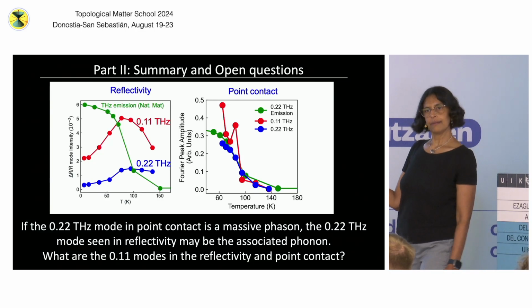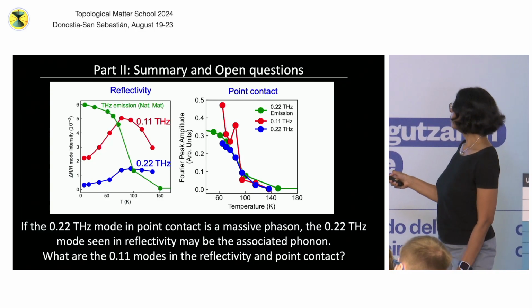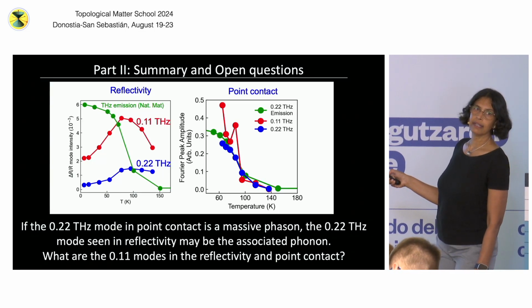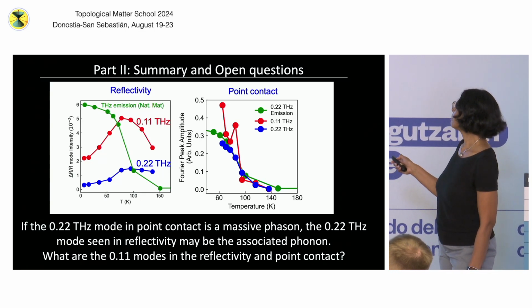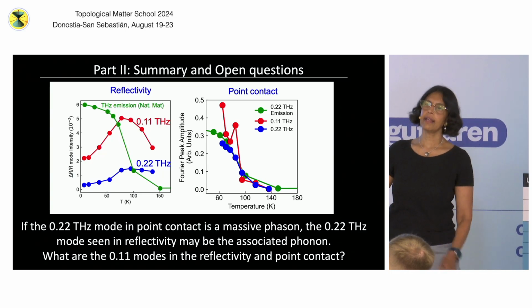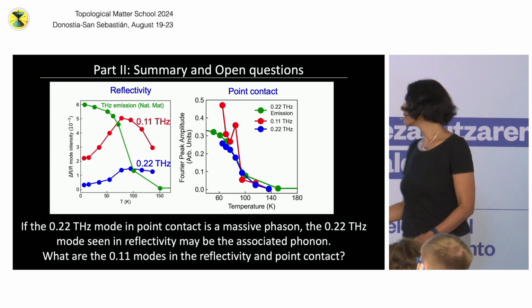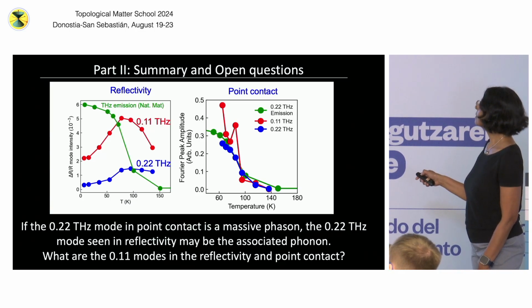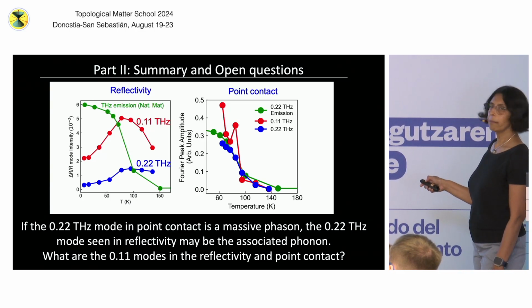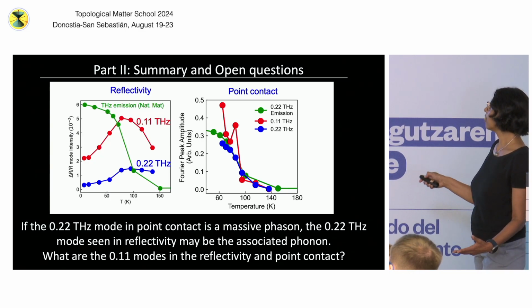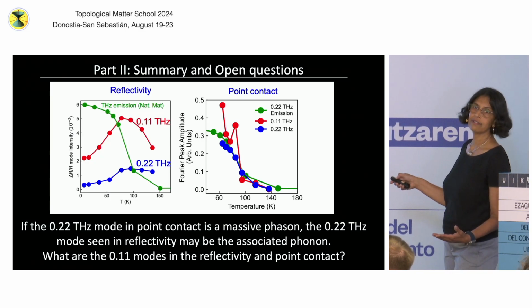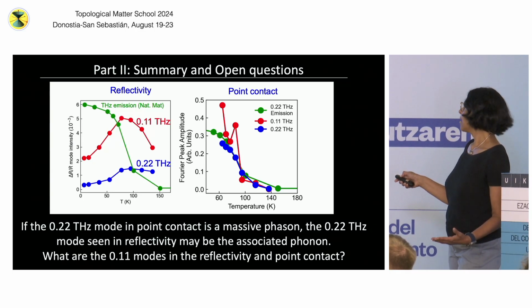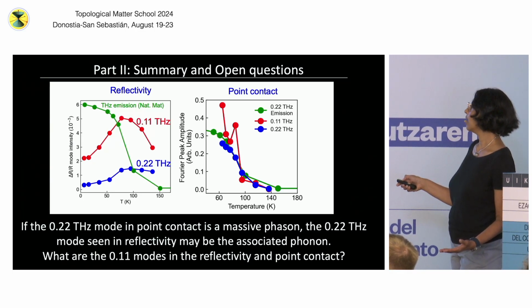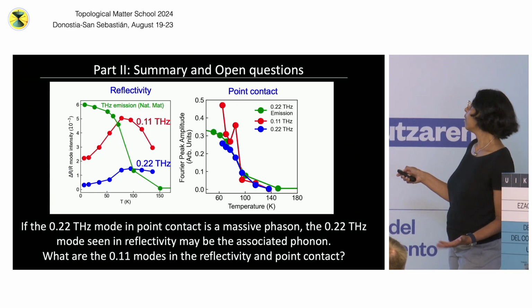You see the same peaks. Okay, I'm going to actually stop here. So this is our data right now. We've measured, using the pump probe technique that I talked about, both reflectivity and point contact by measuring in real time and then taking the Fourier transform and looking for peaks. The reflectivity peaks, there are two of them, 0.11 and 0.22. By the way, Fahad's technique cannot see these 0.11 peaks because they don't have sensitivity at these frequencies. So perhaps what they identified as the 0.22 phason might just be a second harmonic of the 0.11 phason that we are seeing. However, maybe it's something else.